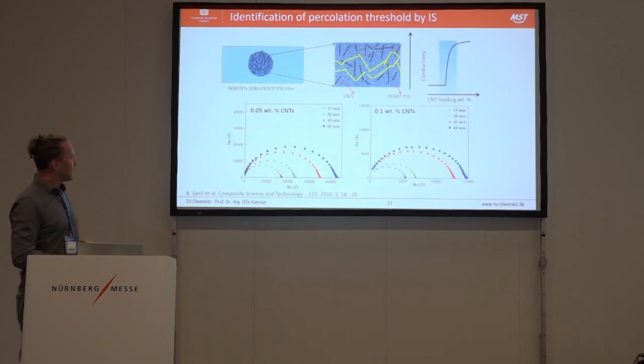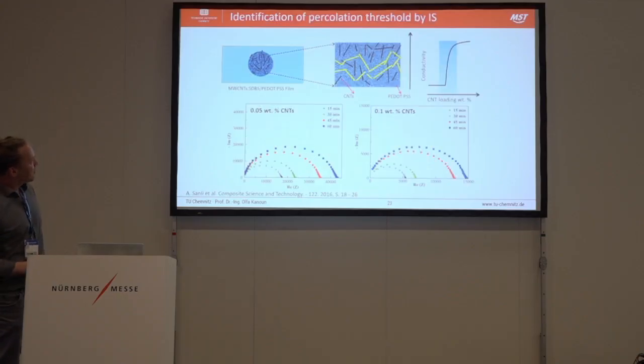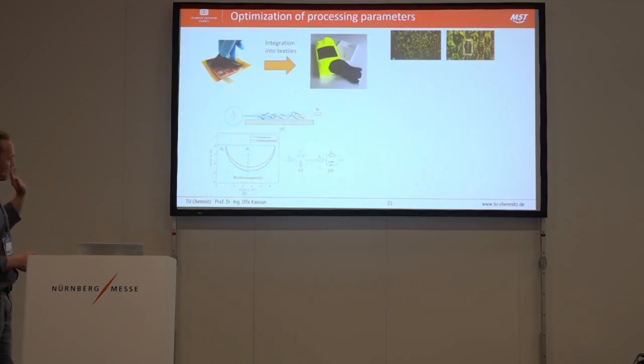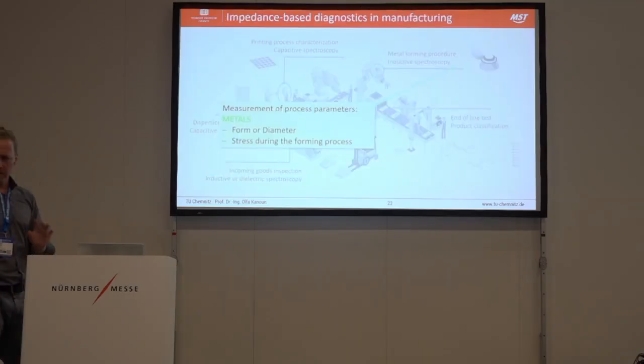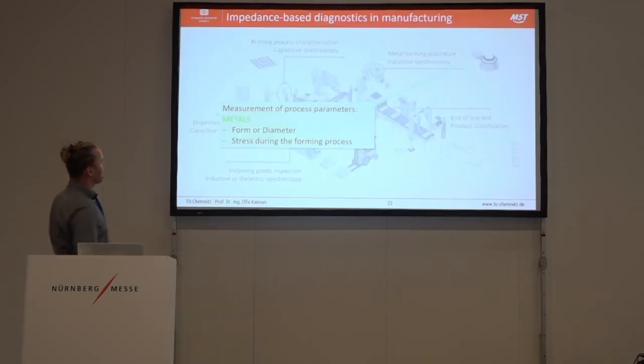We continue. Percolation. This is, for example, our approach for polymer sensors. We have a polymer substrate, and inside we mix carbon nanotubes. We also use impedance spectroscopy to characterize this drying process, which you can see here. We can follow this procedure to optimize it. I go further because time is almost done.